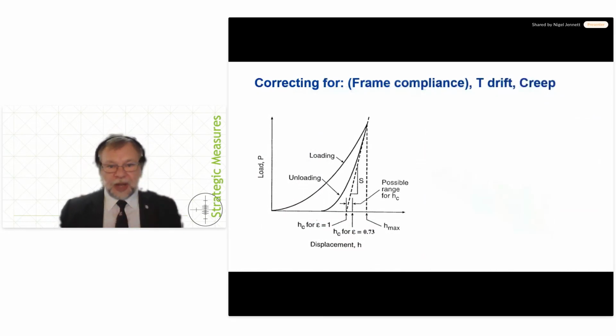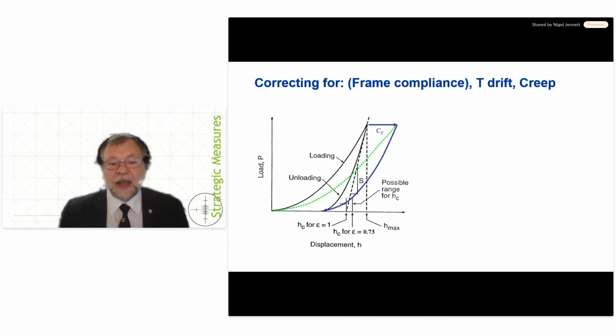So standard nanoindentation: you apply a force, you measure the displacement, and you get a force-displacement curve. And we know that there's a compliance of the machine, which is a displacement that's a function of the force that you apply to the frame of the machine. And you calibrate that so that when you do the force-displacement curve and get the green upward and the blue downward curve, you can then correct it back to what it would be without the compliance. But you can see that the actual displacements at zero force are the same with or without correction, because that's the nature of frame compliance as a function of force.